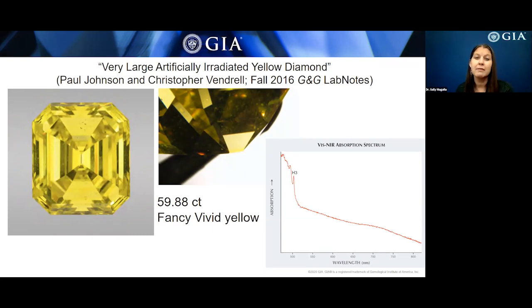On the right, we show its visible absorption spectrum with an unusually strong H3 peak at 503.2 nanometers. The enhancement of that H3 center by the treatment is what causes the beautiful yellow color. And this diamond demonstrates the importance of careful analysis, since even the largest stones may have undergone treatment. So we can't make assumptions about a stone based on its size. Even these very large ones can potentially be treated. And I looked in our database, and this diamond remains the largest one in our GIA database that has been artificially irradiated.